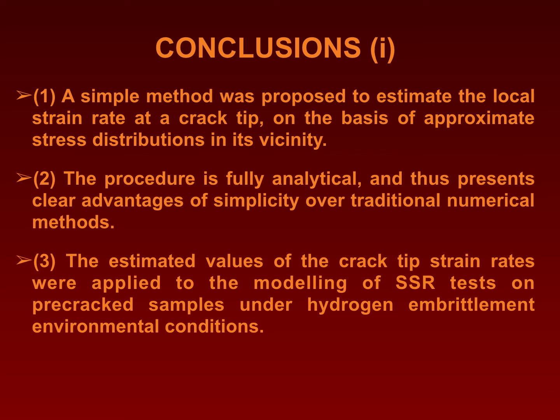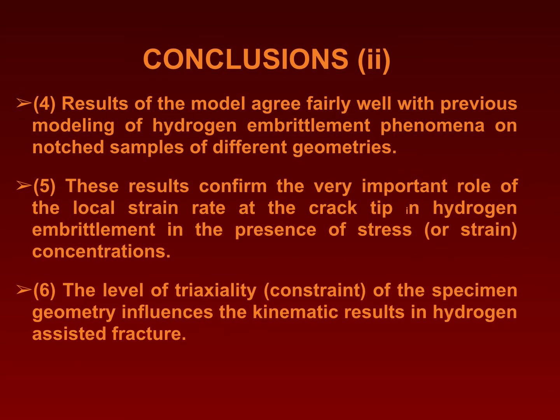Third, the estimated values of the crack tip strain rates were applied to the modeling of slow strain rate tests on pre-cracked samples under hydrogen embrittlement environmental conditions. Fourth, results of the model agree fairly well with previous modeling of hydrogen embrittlement phenomena on notched samples of different geometries. Fifth, these results confirm the very important role of the local strain rate at the crack tip in hydrogen embrittlement or hydrogen-assisted cracking in the presence of stress or strain concentration. The level of triaxiality constraint of the specimen geometry influences the kinematic results in hydrogen-assisted fracture.